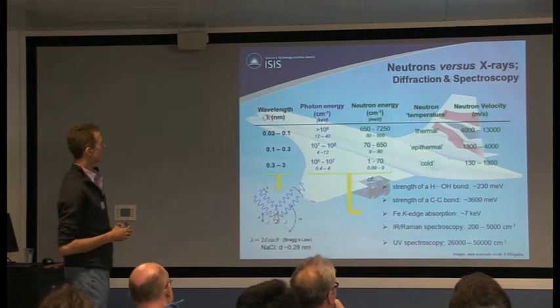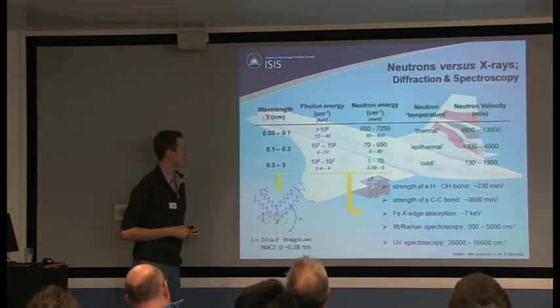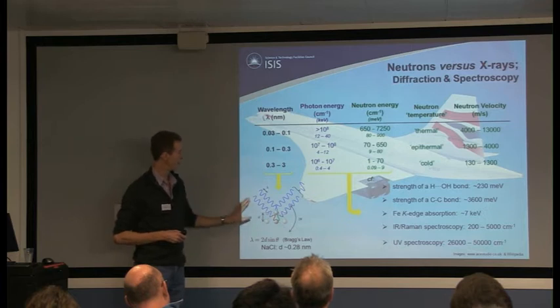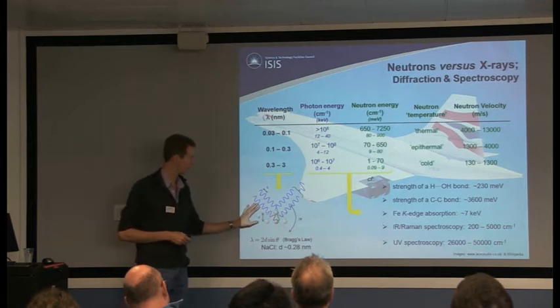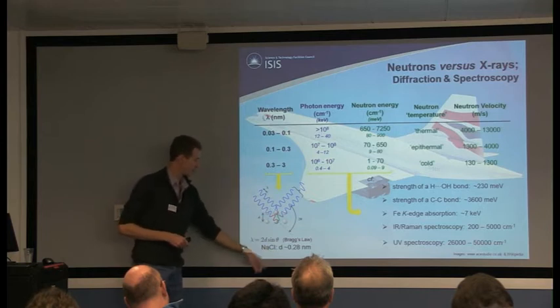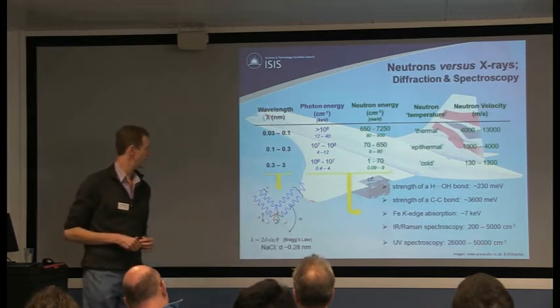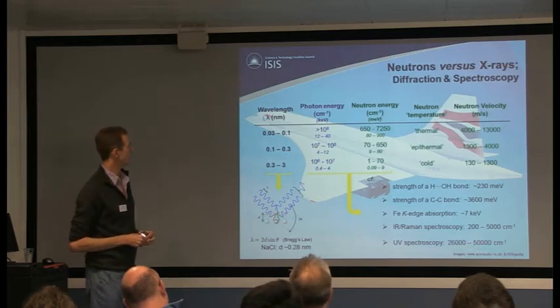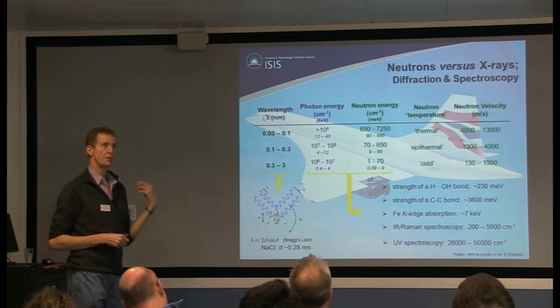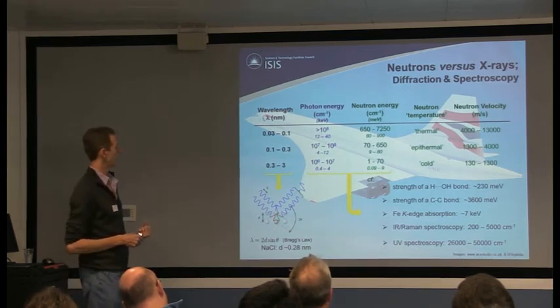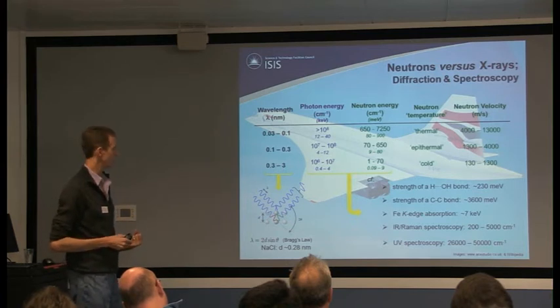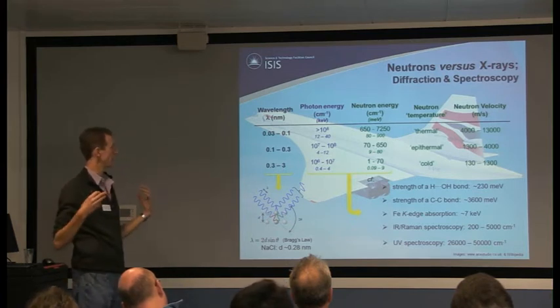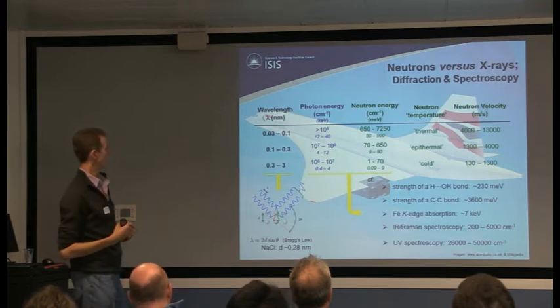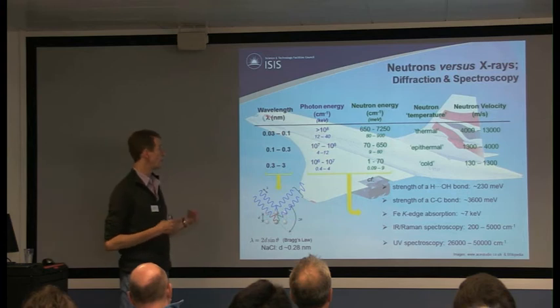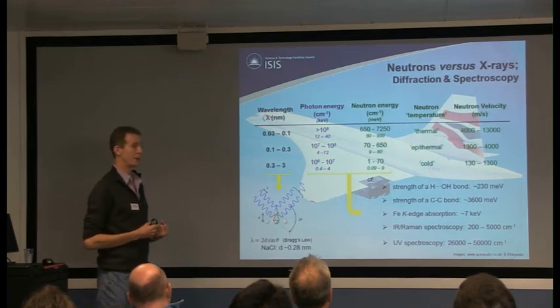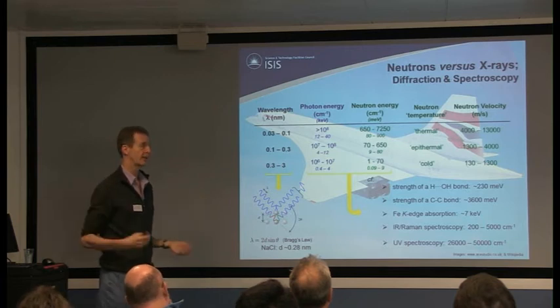Just like X-rays, we can do diffraction and spectroscopy. Diffraction requires wavelengths comparable to the distances you want to study. If you're doing crystallography, looking at something like sodium chloride, you're looking at a bond length of 0.2 to 0.3 nanometers, so you need X-rays or neutrons with a wavelength of that size to see crystallographic diffraction. If you're looking at structure on a longer length scale, several nanometers to tens of nanometers, we can produce neutrons with those wavelengths to study larger macromolecular structures.